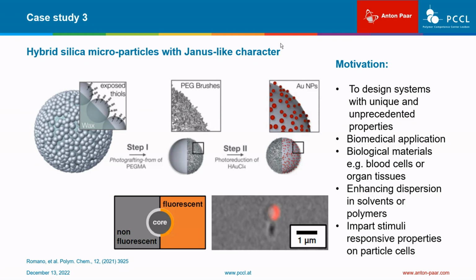In a very recent study, we highlight the synthesis and post-modification of silica-based microparticles with the aim to create particles with Janus-like properties, as you can see here. Functional micro and nano-sized particles have received increasing attention and expanded their range of application in numerous fields. While several studies describe particles which are either inorganic or polymeric in nature, there is promise in particles with a hybrid character. Those so-called hairy particles typically have an inorganic core on which polymer chains are covalently grafted.